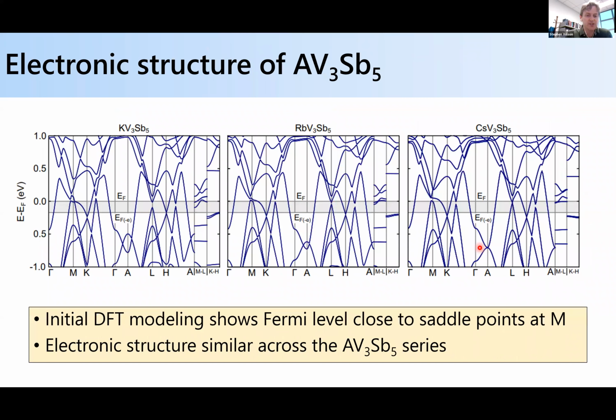Okay. So the initial work looking at the electronic structure of this system is some DFT modeling that was done on the initial report of the discovery of these materials. It basically shows that the electronic structure of these 3 systems is very similar, but the Fermi level is predicted to be rather close to saddle points that are located at the M points at the Brillouin zone edges of the system. Okay, so that's an initial motivation that some of the saddle point physics might be operative in these materials.